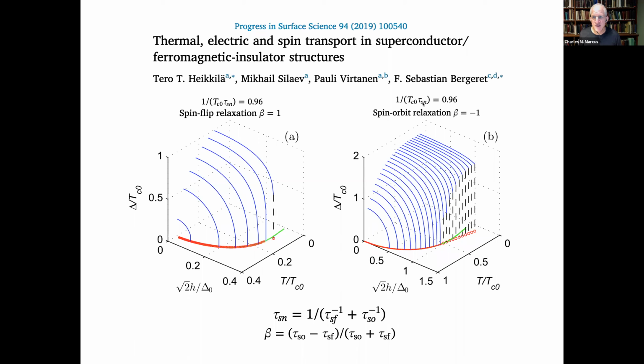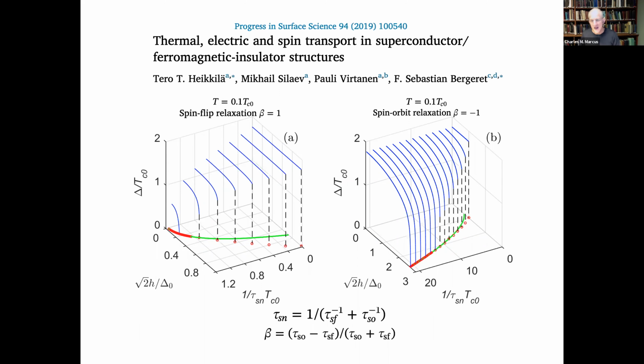This is what happens in the presence of spin orbit coupling. As you move in either with spin flip scattering or spin orbit scattering, the opposite things happen. It's probably better illustrated on this graph, where we now look as a function of either spin orbit or spin flip relaxation. You'll notice I'm using the same notation for this tau Sn, where the inverse of tau Sn is the sum of the rates. And beta changes sign depending on whether it's dominated by spin orbit or spin flip scattering. So here, for positive beta, it's spin flip scattering. For negative beta, it's spin orbit coupling. And then you can interpolate in between.